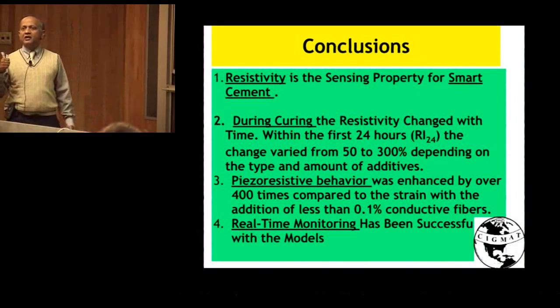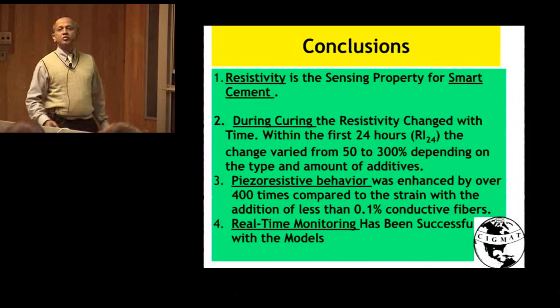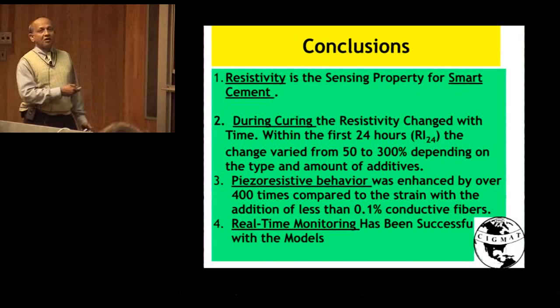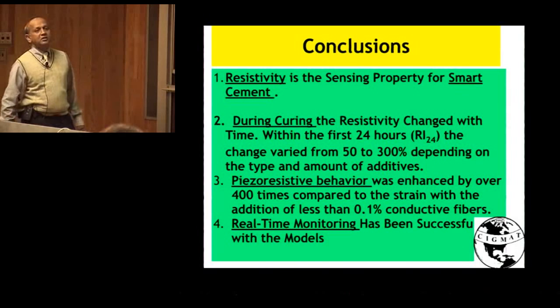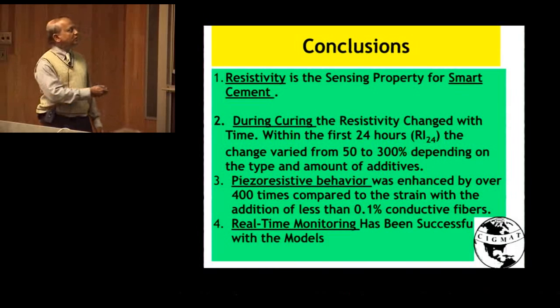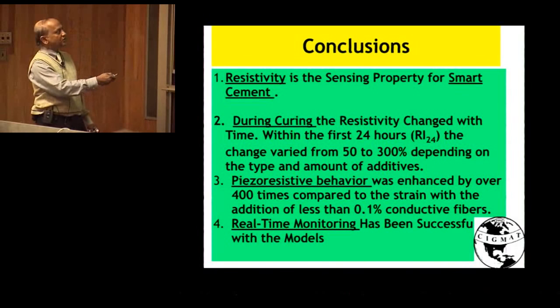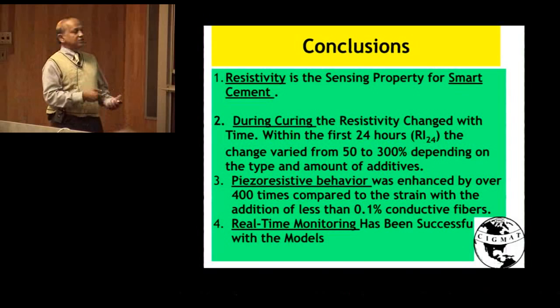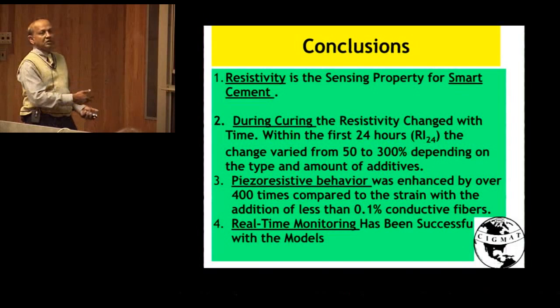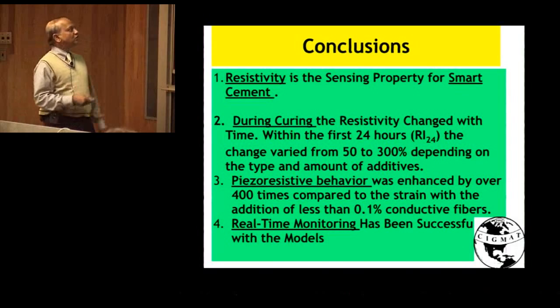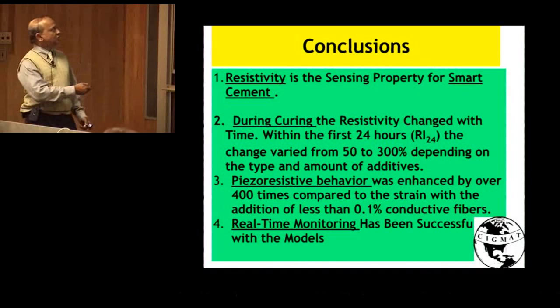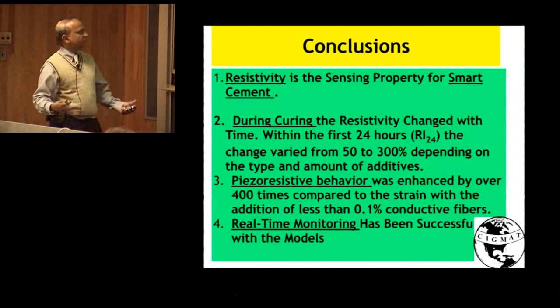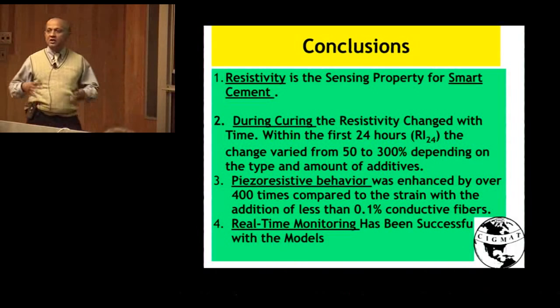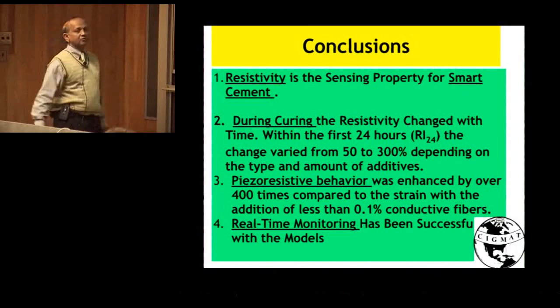Basically, what we have done is we have identified the resistivity to be the sensing property for the smart cement. And you saw the performance of the smart cement. And also, with our approach, you can really monitor the changes during the curing. Within the 24 hours, you can get the RI24, as I told you, the resistivity index 24, which really changes big time depending on the cement mix and the conditions. And that will be a good indicator. Also, we have made the cement to be piezo-resistive. And you can see that it's a very sensitive sensing material as far as stress is concerned. And also, when there is contamination, things change. And our additives are of that order, very small.